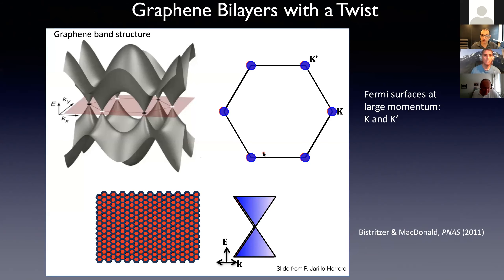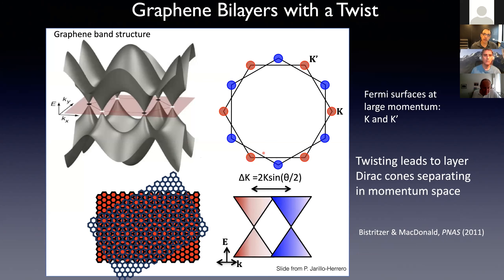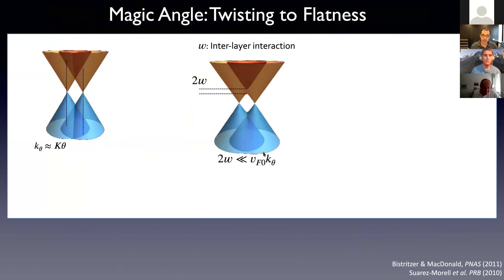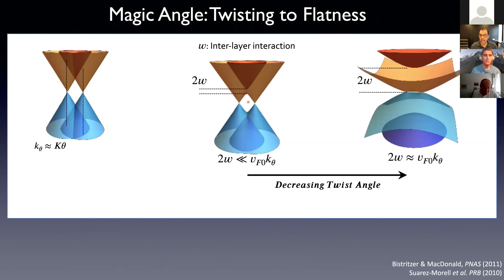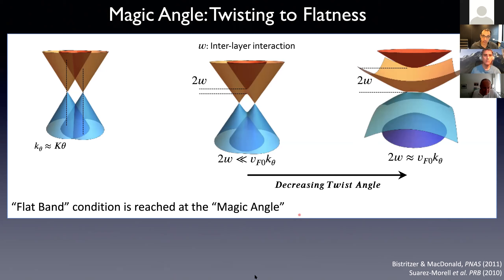Electronically, we have graphene with its Dirac band structure. If you rotate in real space, you're also rotating in momentum space, so you have two Dirac cones at slightly different positions in k-space relative to one another. You can think of these Dirac cones at first as independent. But with tunneling between layers, you have hybridization of the two electronic states. That hybridization modifies the band structure; the touching point between the cones starts to get gapped out. As you decrease the twist angle, this gives rise to a flat band condition — what we call the magic angle.